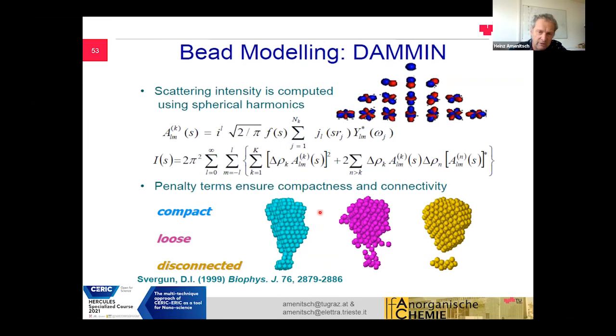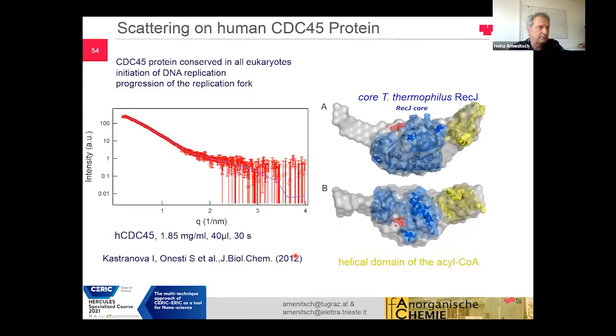The part which is seen in all models is the part you know will be correct, and this fuzzy interface is the resolution limit of the method. Usually the resolution limit is in the order of 1 nanometer, and this is actually quite high. But what is important is that if you have constructs, even these low resolution structures give you already some insights. And this is shown up here.